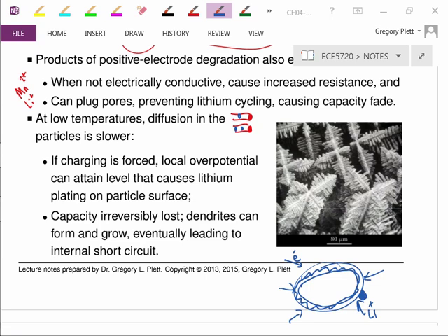This is why we have voltage limits on a cell, as we will discuss in a later chapter on power estimation. If we obey certain voltage limits, we should never lithium plate. We still might, but we should never lithium plate. But if we disobey the voltage limits, we can plate all day long. Well, no, we can't. We can plate until there's no more lithium left, and that happens really quickly. I've had some lab results where we have forced charging of a cell, and within 2 cycles this lithium ion cell was completely gone. There was nothing left. So we forced it at cold temperature. So don't charge your cells at cold temperature too quickly.